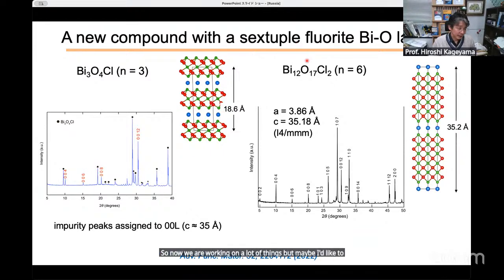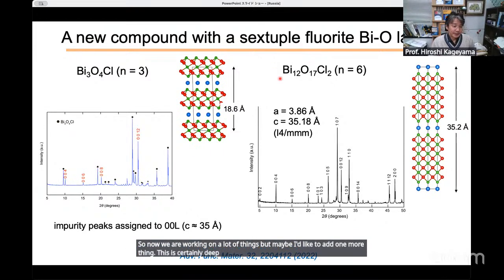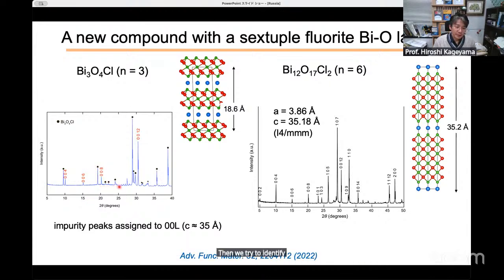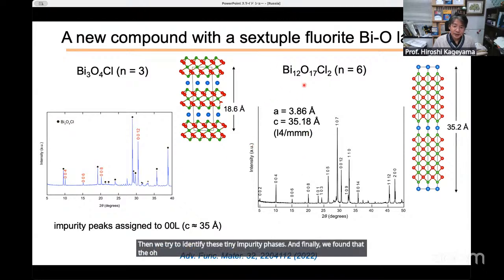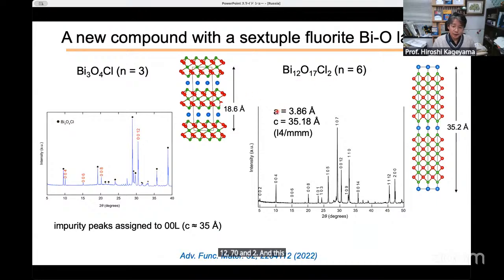Okay. So now we are working on a lot of things, but maybe I'd like to add one more thing. This is a serendipitous discovery. Actually, when we worked on this triple layer system, we found tiny impurity phases. Then we tried to identify these tiny impurity phases, and finally we found that this is this composition, 12, 17, and 2. And this is actually the C-axis corresponding to this 6-layer fluorite structure.